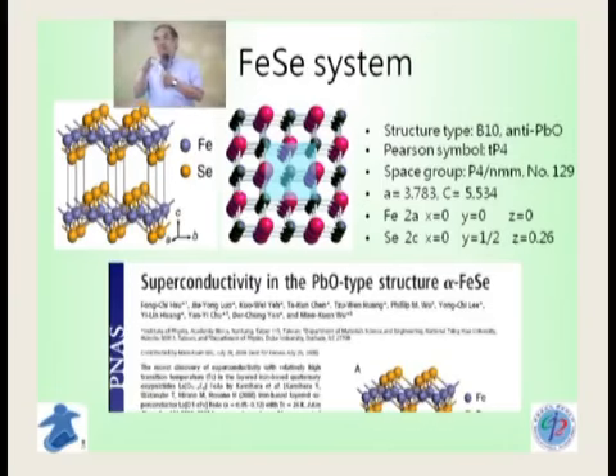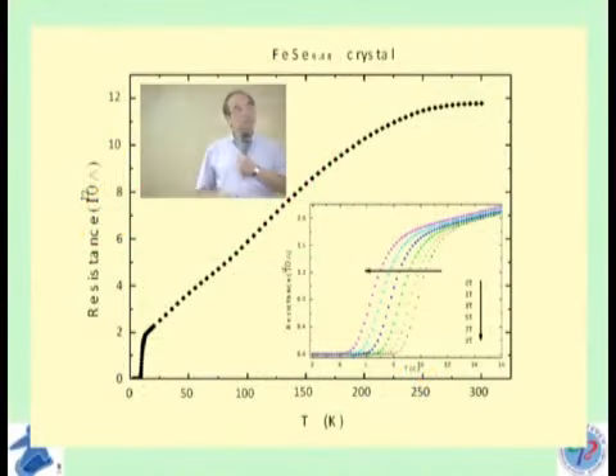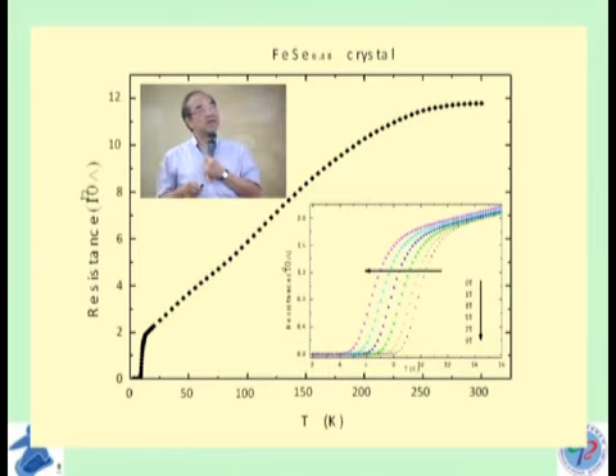tetragonal symmetry. Because the structure is so simple, anything you measure, by looking at a simple property like resistivity or others, you will see some feature. I will show you. For example, this is the first resistivity curve we obtained on this system. Just look at the temperature dependence. You see, there are two features.